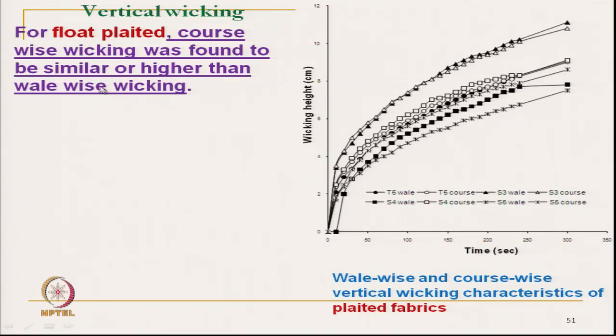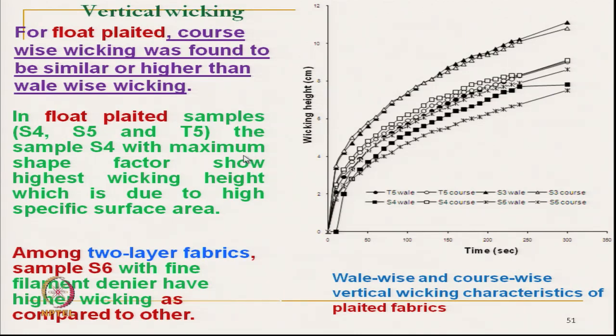Now, coming to the float plated structure, the course wise wicking was found to be the same as, or a little bit higher than, the wale wise direction. Due to the structural difference, the wale wise and course wise liquid flow is almost the same. In the float plated sample, sample 4, which is made of elliptical fiber with maximum shape factor, shows the highest wicking rate due to higher specific surface area.